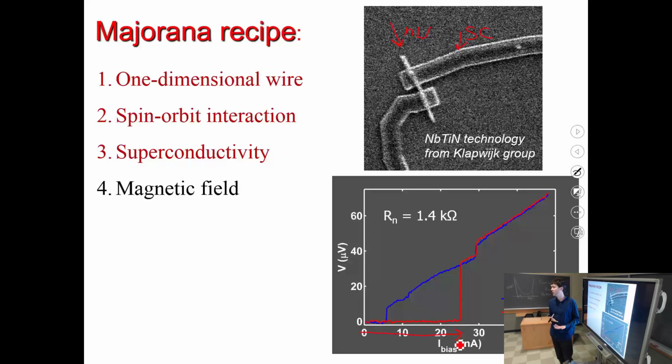And this is the kind of superconductivity that people work with in experiments. It's the induced one. Superconductivity is provided externally by this metal that lives on top of the wire, and the nanowire becomes superconducting by proximity, meaning that Cooper pairs from the superconductor travel into the semiconductor and remember their superconducting correlation for some time or for some distance.